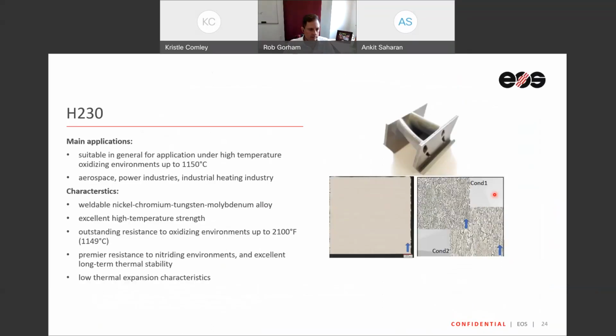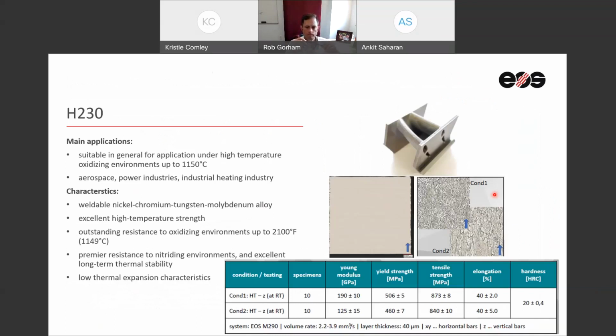Now, talking about Haynes 230, this is another alloy that is very comparable to Hastelloy, but actually has a much higher service temperature as compared. If you see on the earlier plots, it surpasses the oxidation resistance to almost 1100 to 1200 C, which is far higher than what you would expect from Hastelloy. And as you can see, this material as well is possible in additive, and the conditions that we get in terms of mechanical strength are very, very comparable to what you would expect from a casting side.